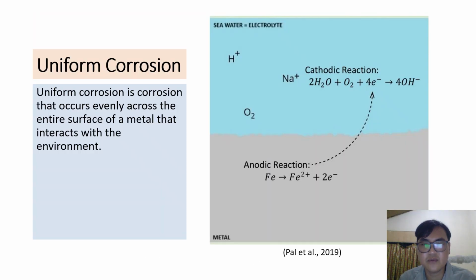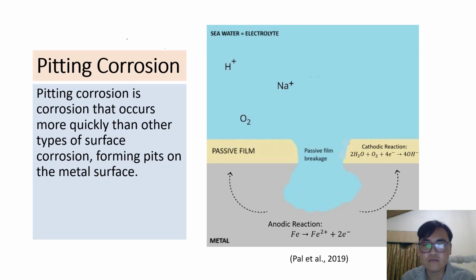One common form of corrosion is uniform corrosion, which occurs evenly across the entire metal surface. However, stainless steel 304 generally resists this well, due to its strong chromium passive layer. A more dangerous form for stainless steel 304 is pitting corrosion. This occurs rapidly and forms deep localized pits on the surface. It occurs when the protective passive layer is breached, often by aggressive ions like chloride found in seawater.